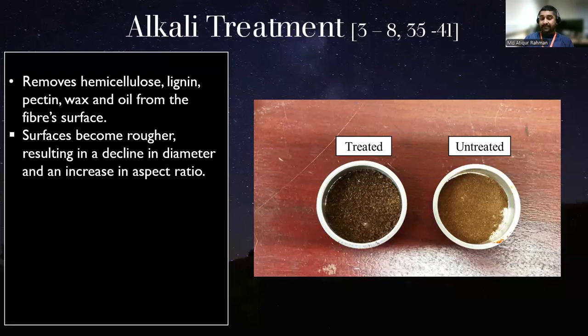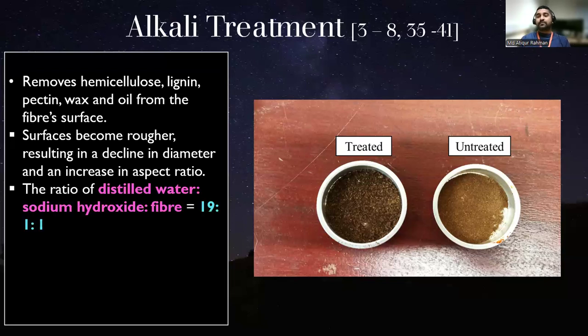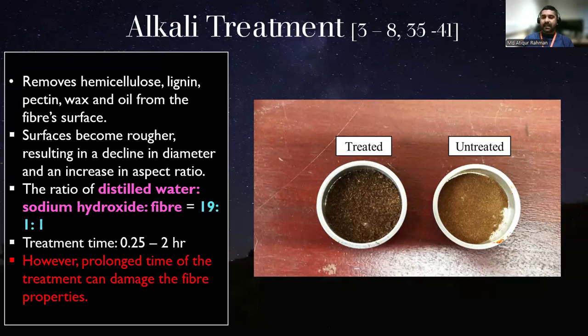Moving forward, we can see that for this particular research, we use the ratio of distilled water, sodium hydroxide, and the fiber equal to 19:1:1. And we use varied treatment times from 0.25 hours, which is 15 minutes, to 2 hours, so that we can see the variation. But there is one thing we need to be mindful of. If we do a prolonged treatment, we have found, even in the literature, that the mechanical and thermal properties deteriorate.